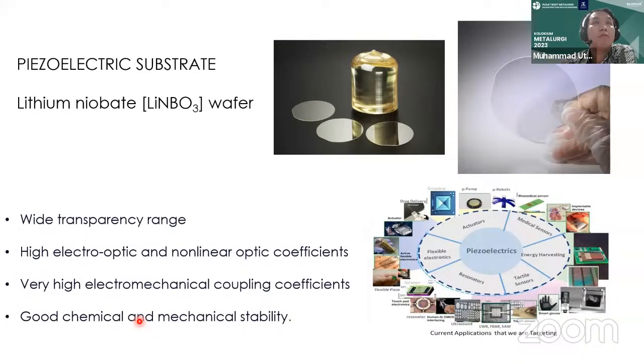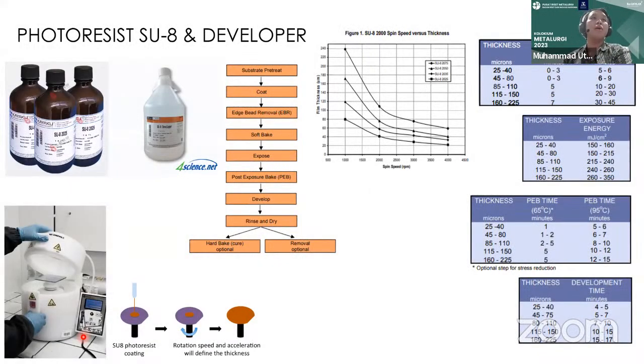And this lithium niobate wafer also has good chemical and mechanical stability. Okay, so the next materials that we usually use in the soft photolithography process are this photoresist SU8 and also its developer. So this SU8 photoresist is a special chemical that can cross-link or harden when it's exposed to UV lights. So it's something like this. It's kind of like a thick viscous liquid, and this is the developer.